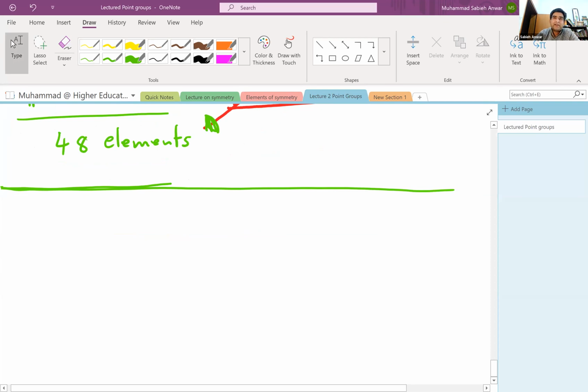If you look at the 27 point groups before the cubic point groups, in all of them, the symmetry elements pass through a single point, and there is a principal axis of rotation. In the 5 cubic point groups, there is no one principal axis of rotation. There are multiple axes of rotation, and it's possible that the axes of rotation do not pass through a single point. There's no principal axis of rotation in the cubic point groups, in short.